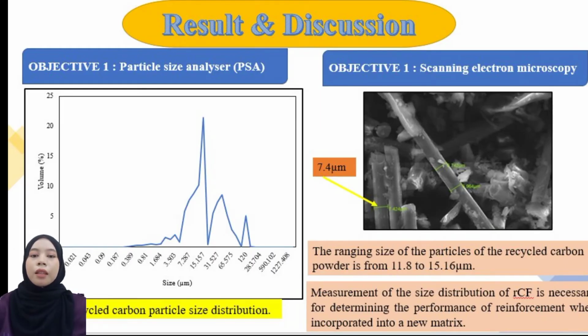The graph shows the recycled carbon particle size distribution. The size range of the recycled carbon powder particles is from 11.8 to 15.16 micrometer. Measurement of the size distribution of recycled carbon fiber is necessary for determining the performance of reinforcement when incorporated into a new matrix. The SEM obtained shows the fiber to have a cylindrical shape, and therefore the micrograph was used to determine the diameter of the fiber. The diameter of the recycled carbon is about 7 micrometer.